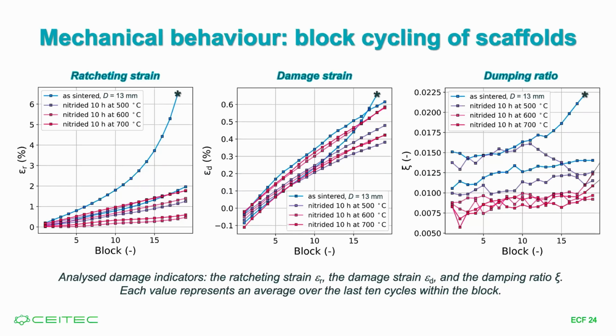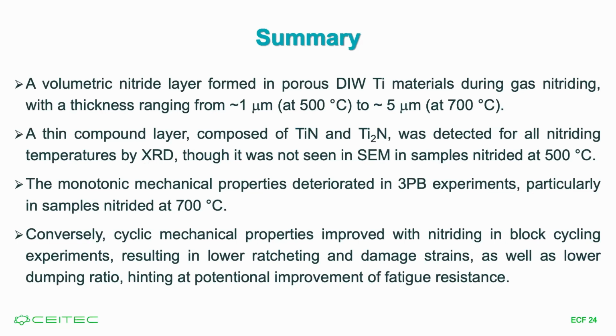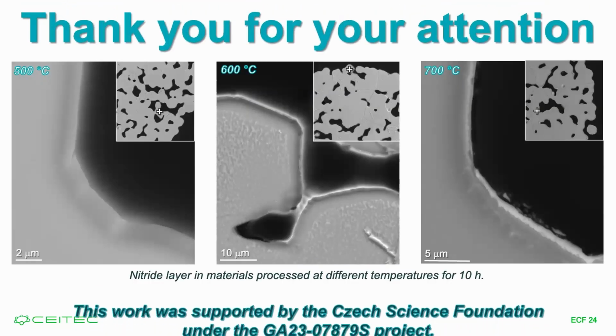I'm sorry, it's many images and it's unfinished work, but let me summarize. We are able to do volumetric nitridation of these materials at temperatures as low as 500 degrees Celsius. Compound layer is composed of these two nitrides. We detected them for all samples. And we see that mechanical monotonic properties deteriorate, particularly at 700 degrees Celsius. And it seems that cyclic properties may be improved by gas nitriding, which we hope to see later. So this is everything. Thank you very much for watching.